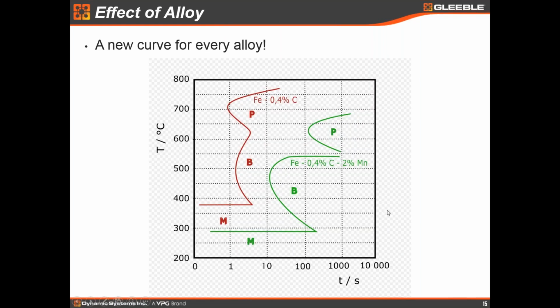This just illustrates a little bit what I have just described, that the alloy is very important here. So this is simply the two CCT diagrams for the same steel, except one has no manganese. It's a 0.4% carbon steel. One has 2% manganese. So you can see the manganese shifts all these curves over to the longer timelines.